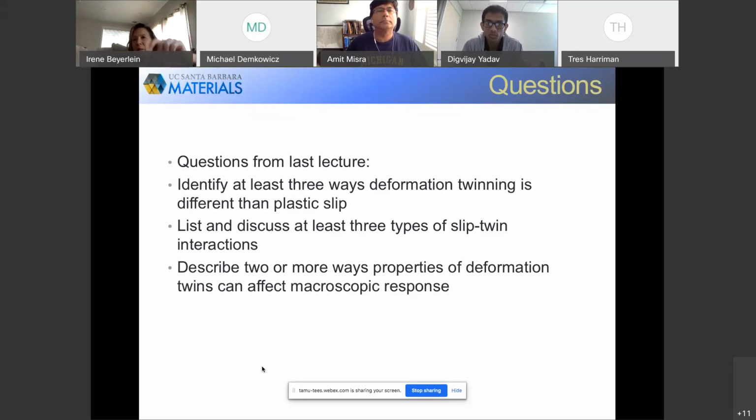The shorter that step height, the less atomic shuffling you have, but the higher the elastic energy or the Burgers vector between the planes. And what ends up happening is it's just easier for the twinning dislocation to move if it has less atomic shuffling. So it is affected by the atomic shuffling part of the transformation. Okay, sure.